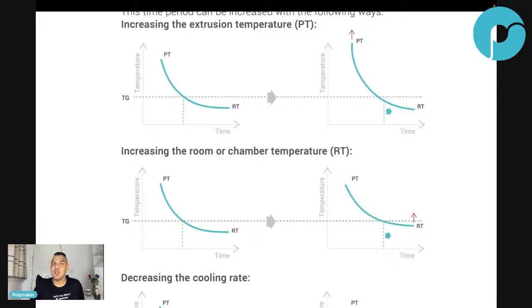What is the challenge? What is TG? TG in amorphous material gives the heat resistance of the material. ABS, heat resistant 100 degrees, PETG 80 degrees, PLA 60 degrees, I don't know, PC-PBT 130 degrees, etc. So what's the challenge? People want high temperature material. People want easy to print. You get the challenge? The higher the TG, the harder it is to print, because it won't release the stress. So the higher the TG, the harder it is to print, because it will warp. But the higher the TG, the higher the heat resistance. So you get the problem now when people ask for high temperature, but that it prints well, for amorphous material.